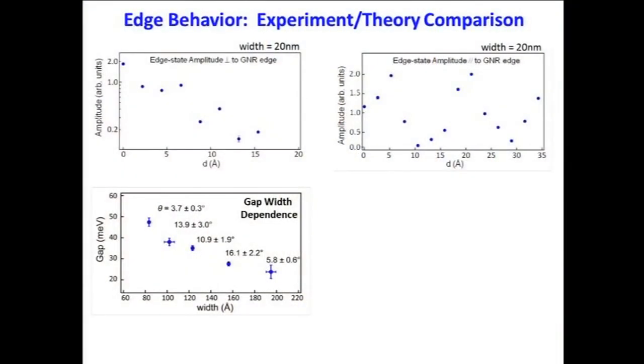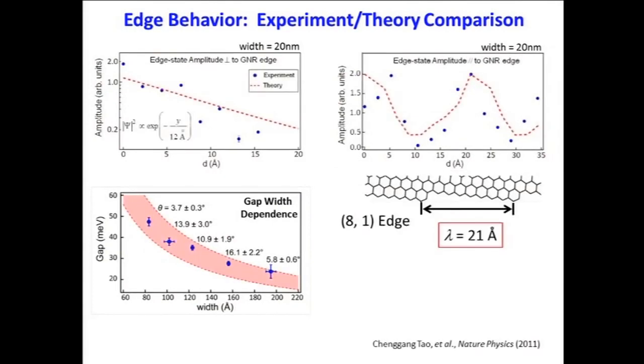So we can also compare, now that we have this nice theory, our other results, the spatial dependence of the edge state, to their theory. So here's the spatial dependence as we move perpendicular from the edge, parallel to the edge, and the width dependence of the edge state energy gap that we measured experimentally. And here's what they calculated using their tight binding model. And in red is the theory.